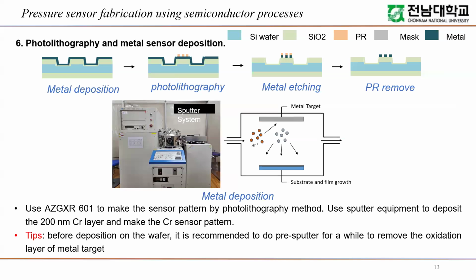After that, we make a sensor pattern on the silicon wafer, using this sputter machine to deposit the chromium sensor layer. Before deposition on the wafer, it is recommended to do a pre-sputter for a while to remove the oxidized layer of the metal target. Then we use argon ions to hit the chromium metal target, and the chromium ions fall down onto the substrate and the film will grow. Our desired thickness was a 200 nanometer chromium layer.